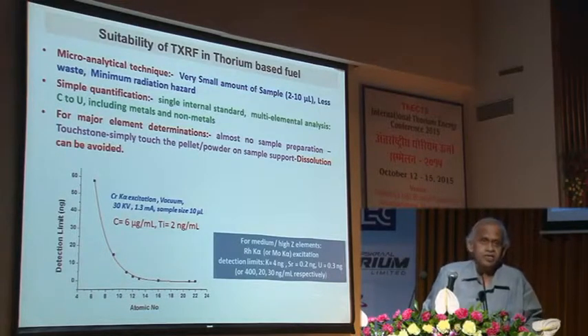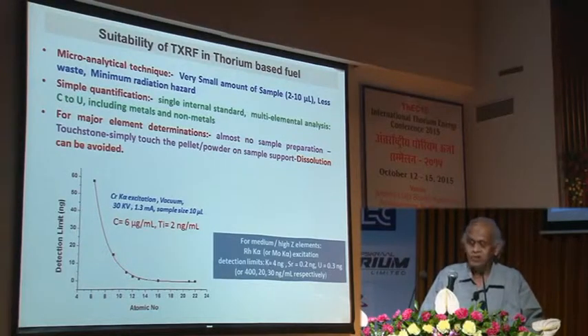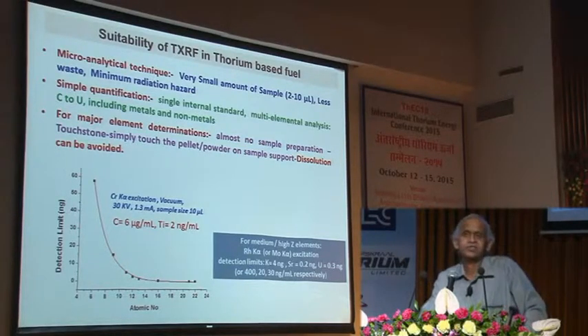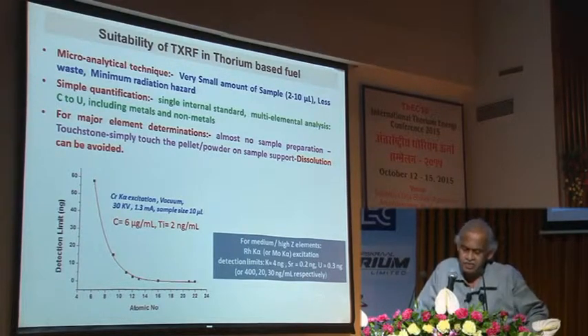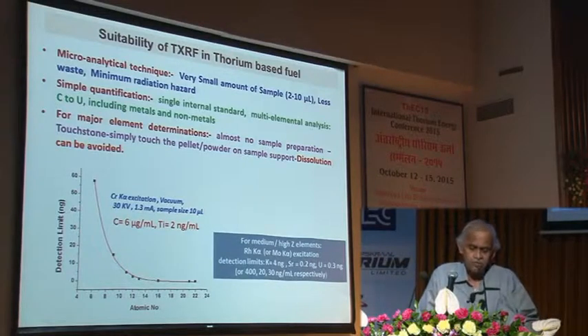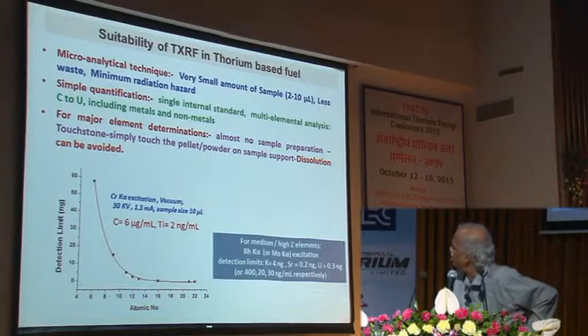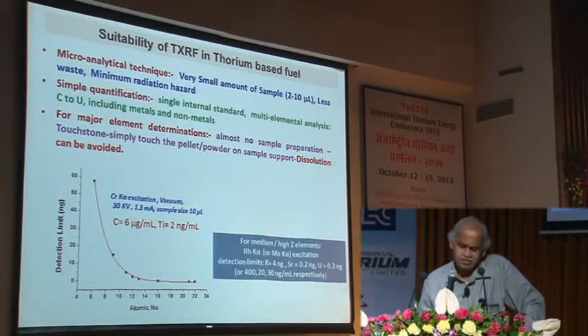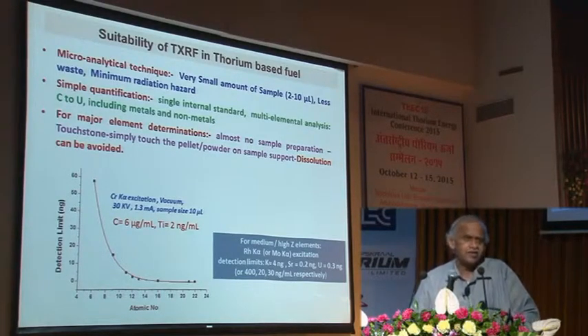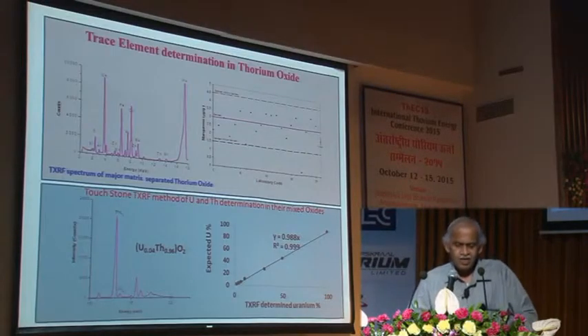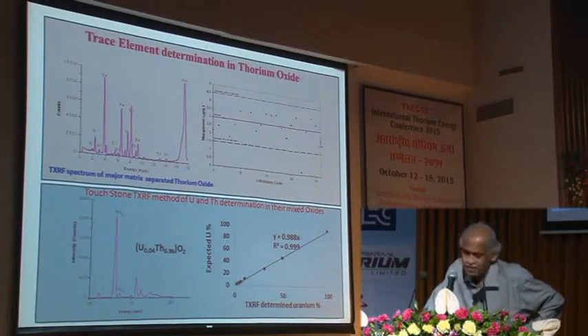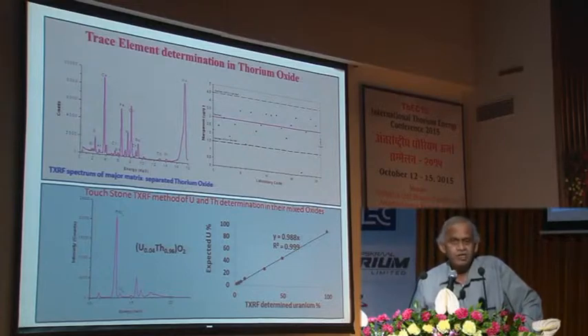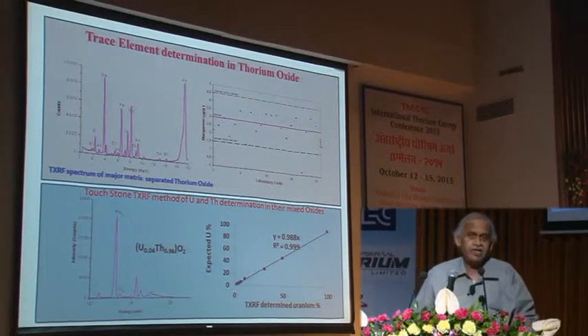And another important technique that we have developed is the total reflection X-ray fluorescence technique for thorium-based fuels. This is a microanalytical technique using very small amounts, 2 to 10 microliters or less, resulting in a very minimum amount of waste, and of course very simple quantification. What we need is only a single internal standard, and I can go for a multi-element analysis from carbon to uranium, including metals and non-metals. For major element determinations, no sample preparation is involved; we just crush the pellet and put that wafer under the TXRF, and we were able to realize the technique. And of course this is how we have used and calibrated the technique for trace elements in thorium oxide.